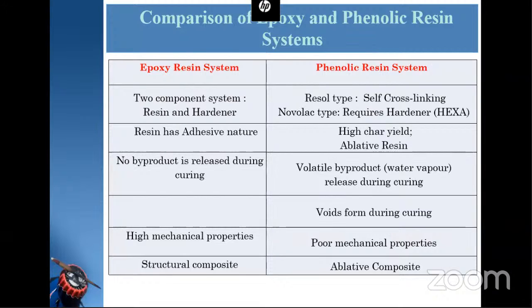If you look at phenolic resins, which we are using widely for our missile applications to make the structures in nozzles, which have to withstand very high temperature, and the re-entry vehicle structures, we are using phenolic resin. There are two types of phenolic resins. Resole type is a self-cross-linking phenolic resin. Novolac requires a hardener. So this phenolic resin is a high char yield material and an ablative material.